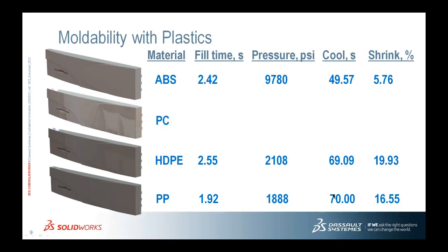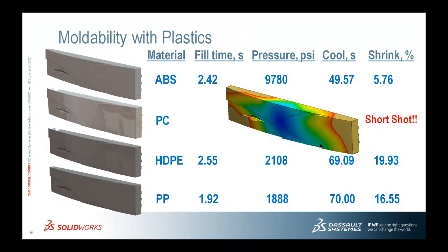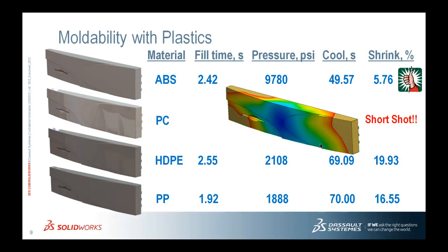Now, polycarbonate, which was the material with the smallest thickness, was actually not injection moldable using that machine. We actually achieved short shot. We can pretty much eliminate PC from our material choices. And in this case, I would argue that ABS might be the best material. Now, there are some issues that, depending on your specific design criteria, might push you to one of the other plastics. For instance, ABS did require a little bit more pressure. Now, if that could be a potential problem for you, then you might want to pick HDPE or PP.